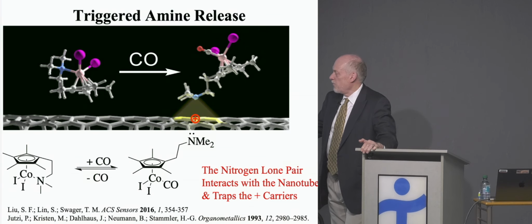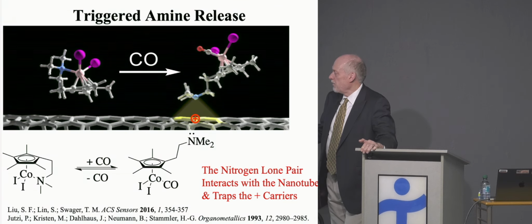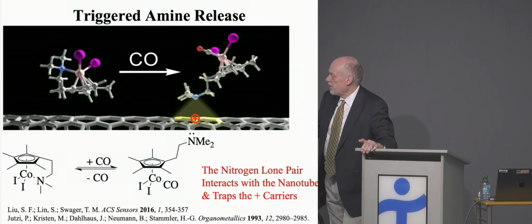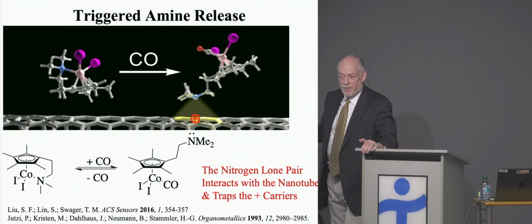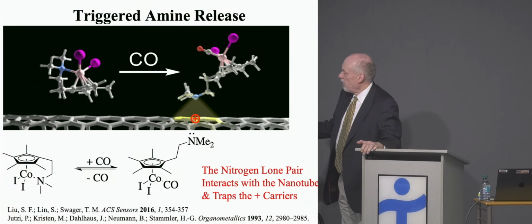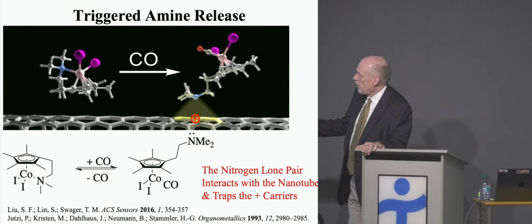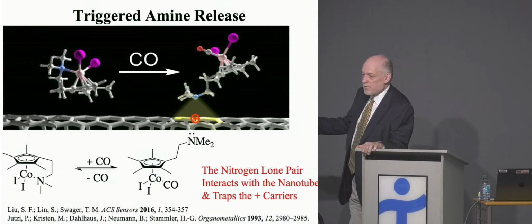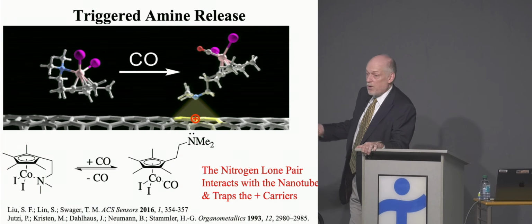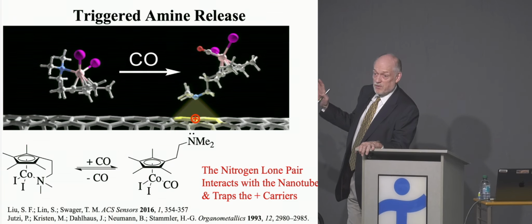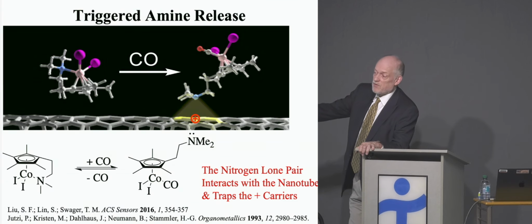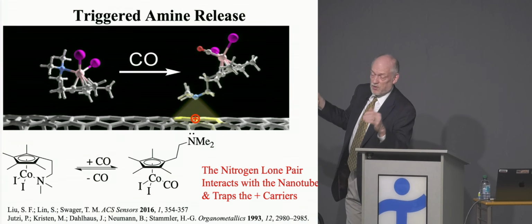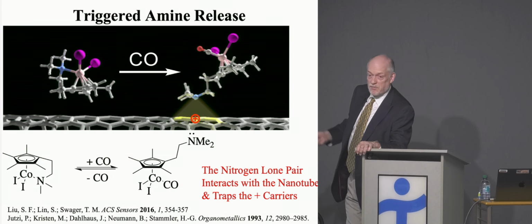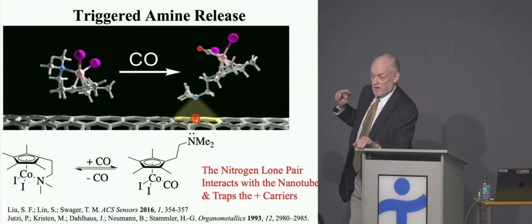Okay, so this is what we call a substitution reaction. And without carbon monoxide, it really lives over here. But every time this pops off, even for a little bit, if carbon monoxide takes its place, it gets stuck over here. And when it gets stuck over here, this nitrogen has what's called a lone pair, and that lone pair loves positive charges. So the nanotubes now have these positive charges in them because molecular oxygen in the air essentially extracts electrons, and when you have this, it basically pounces on it and it captures it and it stops it.